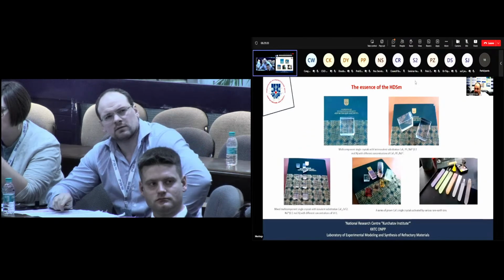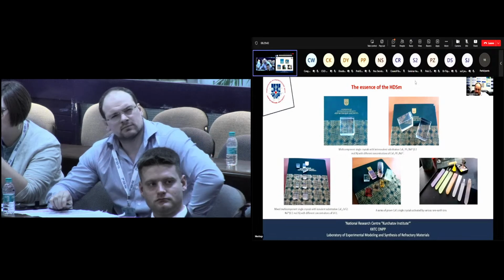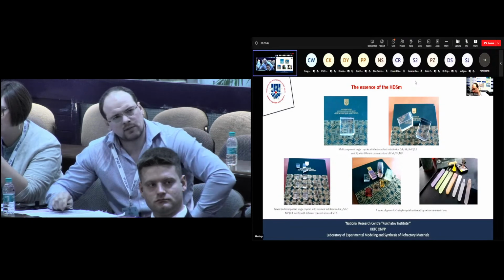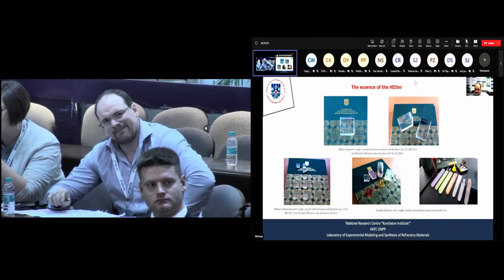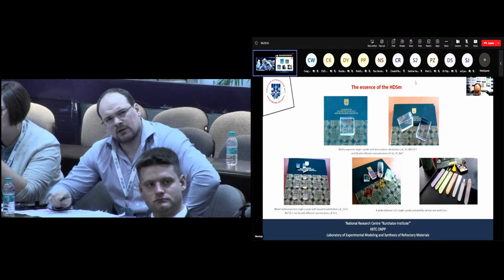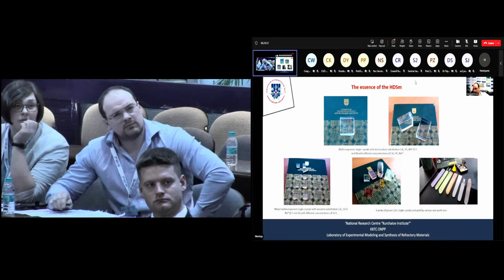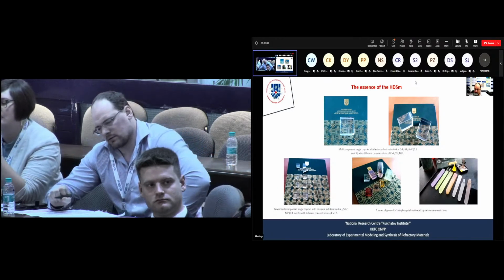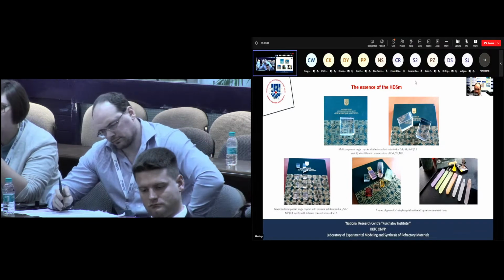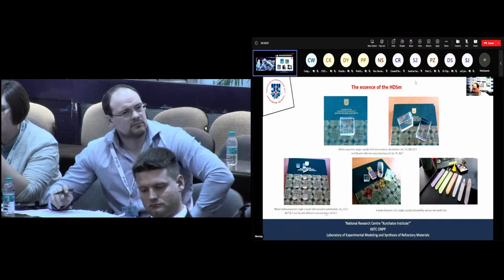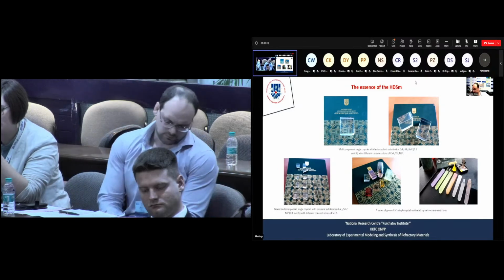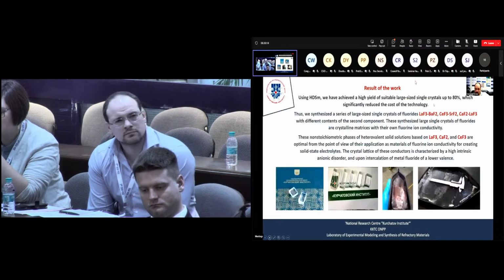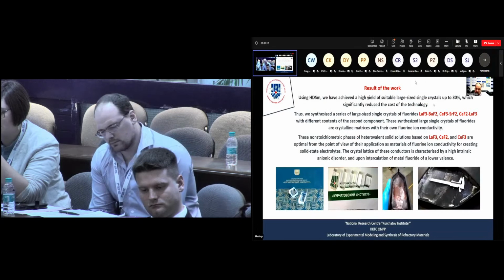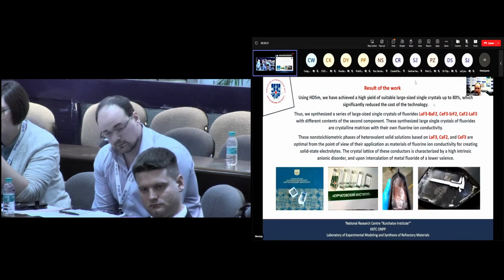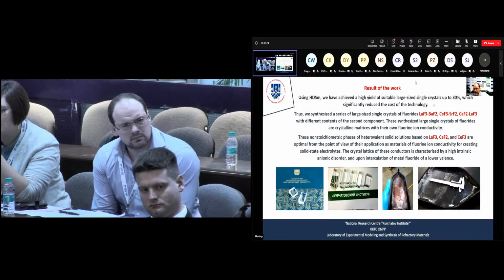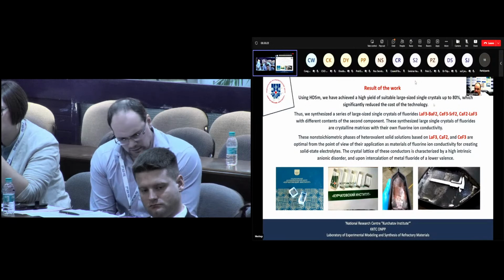Using this method, we were able to synthesize simple fluorides with fluorite structures such as calcium fluoride, barium fluoride, and strontium fluoride, as well as single crystals of rare earth-doped compounds such as calcium fluoride doped with europium, cerium, thulium, and so on. Using the HDSM method, we have achieved a high yield of large-sized single crystals, up to 80%, which significantly reduces the cost of the technology.